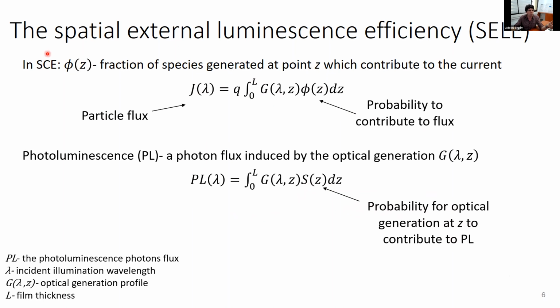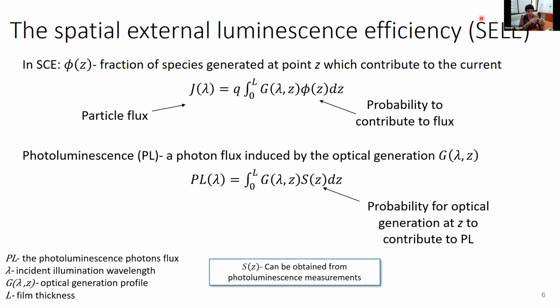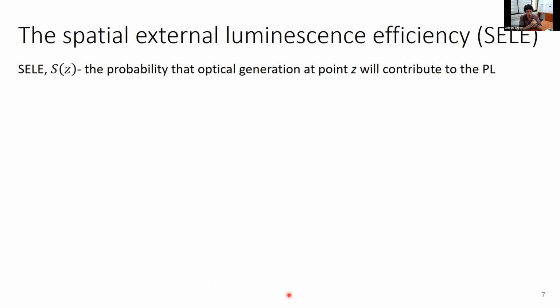And this is what we call the spatial external luminescence efficiency, SELE. So again, by looking at photoluminescence quantum yield as a function of the incident wavelength, we can extract the SELE and maybe get some understanding of the photovoltage. But this is not all. Maybe there's some other interesting aspects to this. So once again, a good solar cell is a good LED.